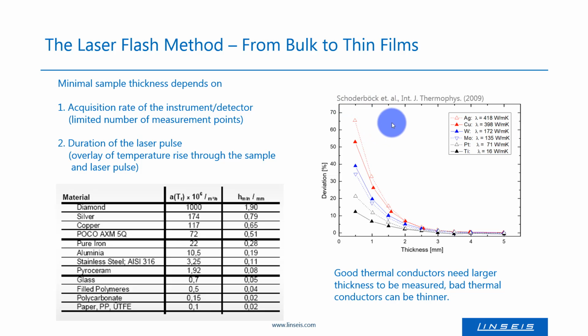It is also rather easy to imagine that a thermal wave conducted through a 3 mm thick polymer sample takes much longer to reach the front surface than the thermal wave through a 100 nanometer thin gold layer. This is illustrated in a table which lists the thermal diffusivity and minimal height of different materials for the LFA measurement. The timescale changes from the millisecond region to the nanosecond timescale.